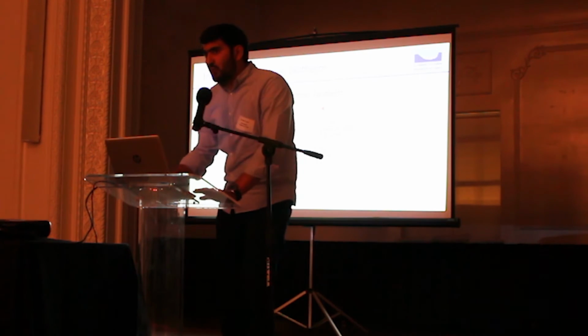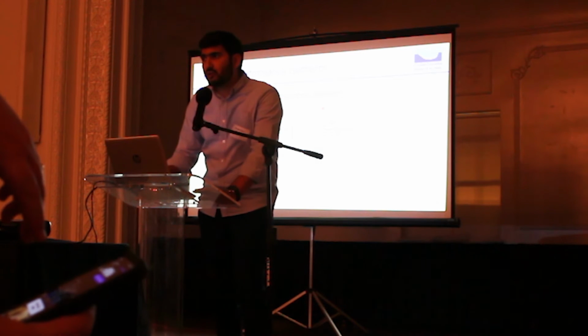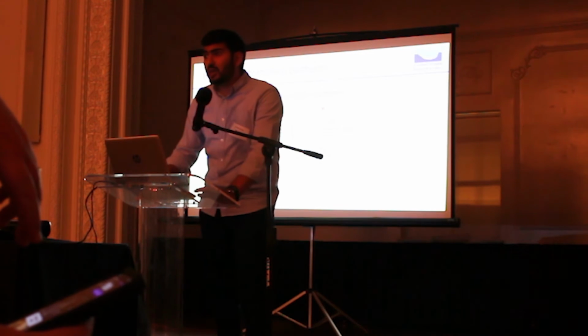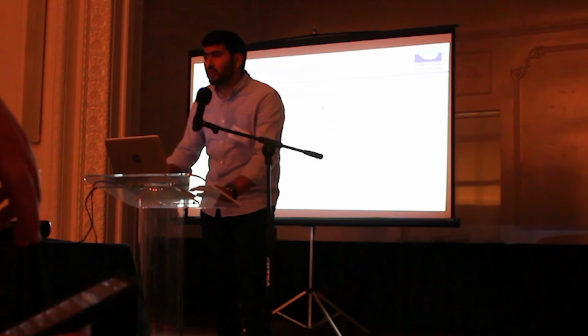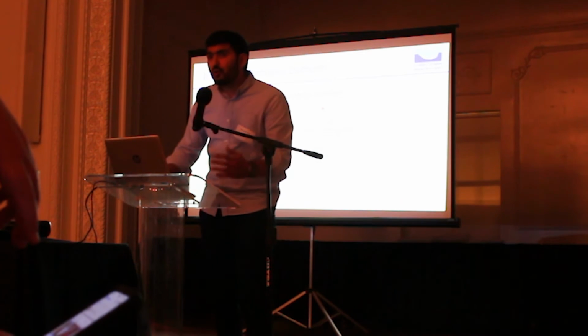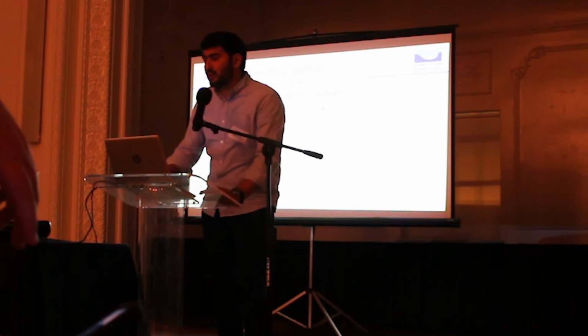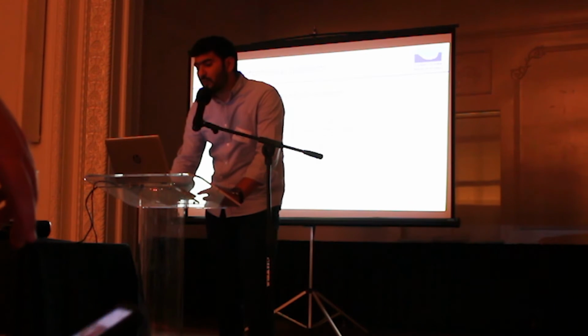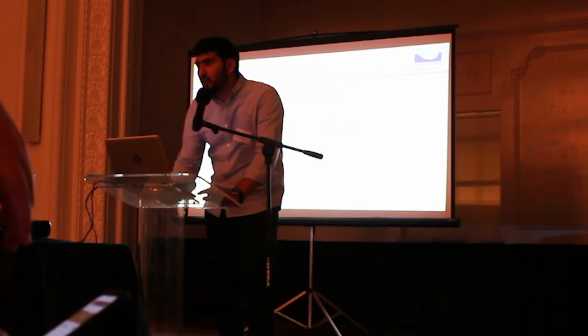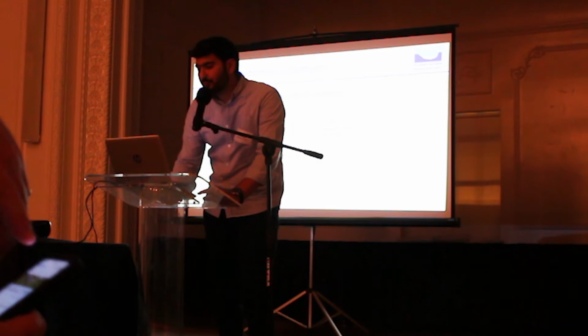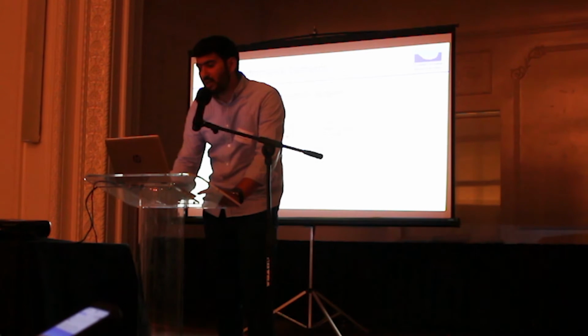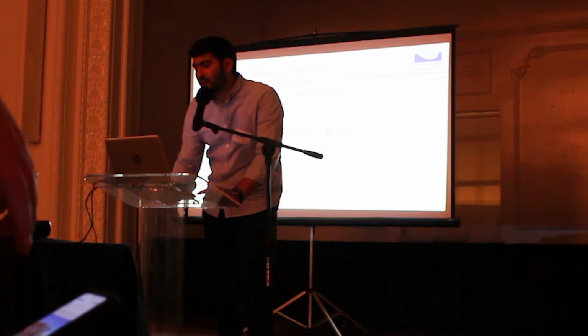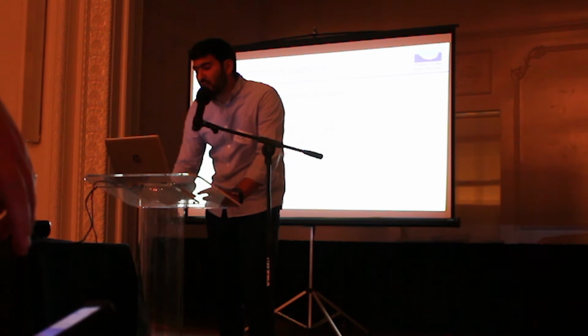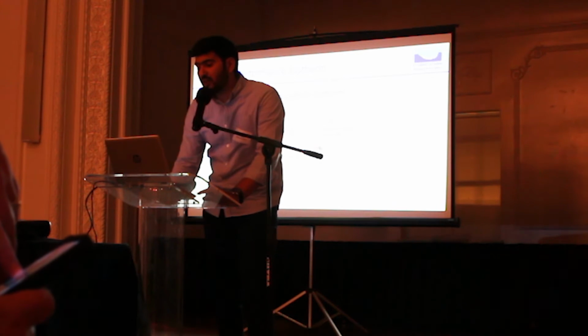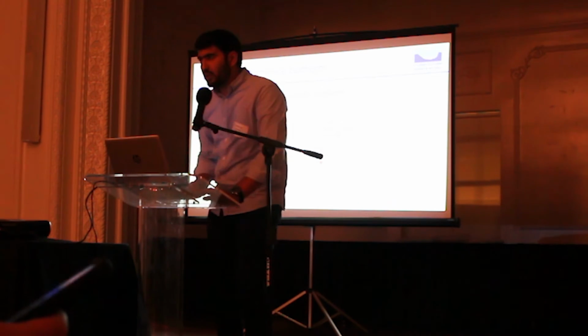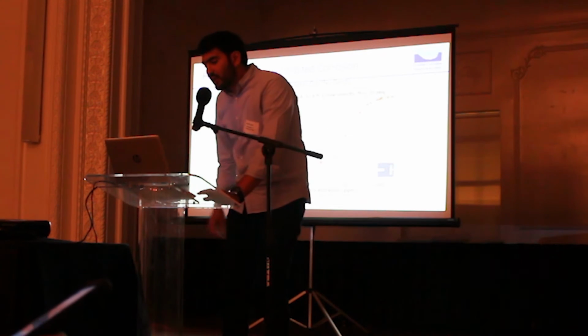Based on studies that we have done at the Erosion Corrosion Research Center of the University of Tulsa, we have found the Frumkin adsorption isotherm to be the best representative model for studying the performance of corrosion inhibitors in the presence of solid particles. As we can see here, the Frumkin isotherm was modified so it accounts for changing temperature and erosion rate. It is also used to develop a relationship between the inhibitor concentration and the surface coverage by the inhibitor, theta. The surface coverage by the inhibitor, theta, is given by one minus inhibited corrosion over uninhibited corrosion.